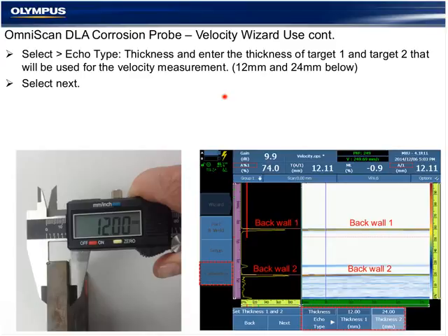So if a velocity measurement using the wizard has to be made, it's made on one A-scan, and we do not use the nominal thickness of the pipe or plate. It could be out 10%, which would be normal.